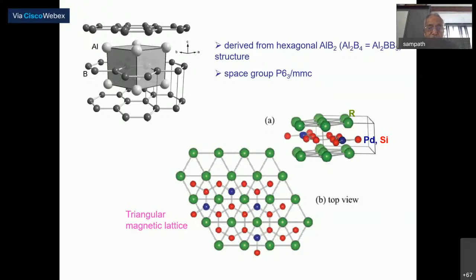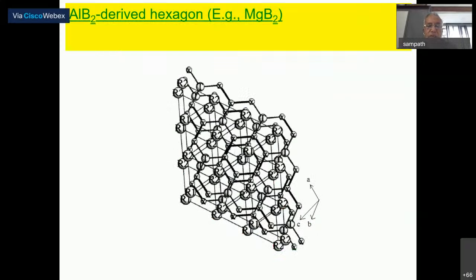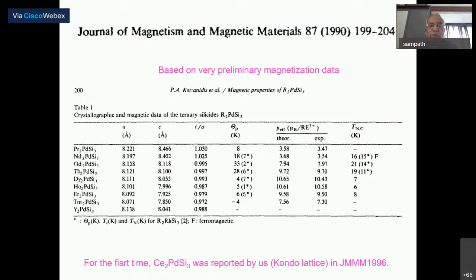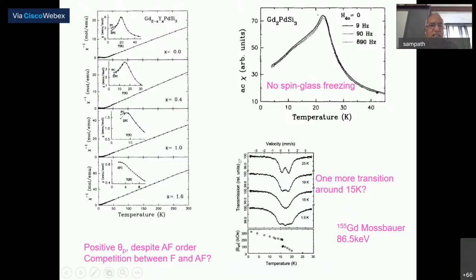In this family, we have published about 50 papers till now, in Physical Review Letters, Physical Review B, bringing out all kinds of anomalies due to magnetic frustration in this family. Okay, this is another view along the C-axis, which is basically a honeycomb structure. You could say there are two different sites for the rare earth we are getting. Now, the first paper on this family was published in 1990 by a chemist, and there they report only very preliminary magnetization data, from which one can basically determine only the magnetic moment. So we have studied this family, the entire family, very exhaustively, both on polycrystals and single crystals, using a variety of experimental techniques.